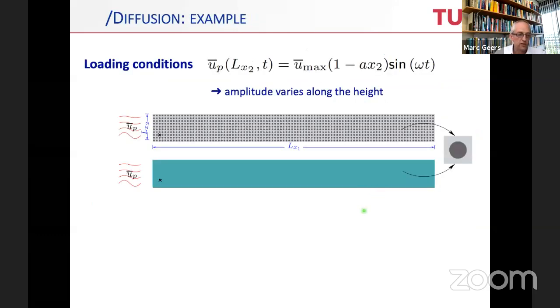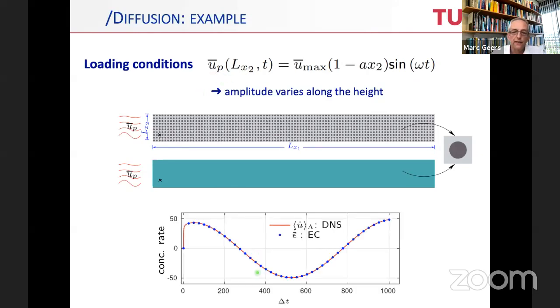Let me show you also an example for the diffusion case. So here's the heterogeneous material. It's replaced by a homogeneous one. The amplitude of the concentration that is actually imposed on it varies along the height. And again, you can make a comparison with direct numerical simulations that are computed on the top problem and see whether your effective continuum, which is that enriched continuum, actually stays on top of the DNS simulations, and it does, right?